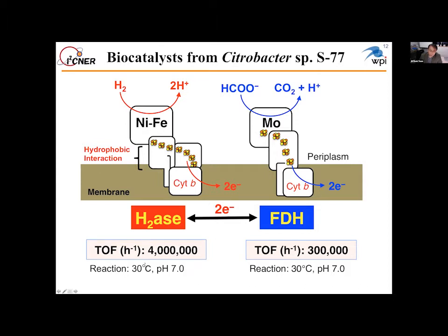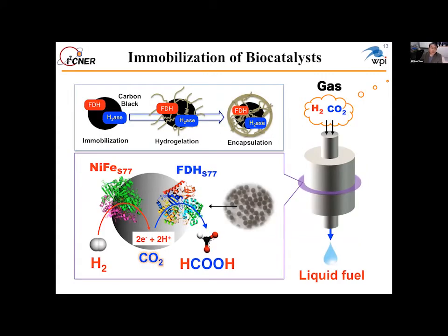Because as you see here, this enzyme is very active. Even in just 1 hour it's reactive, and it can last over a week, but even in 1 hour the activity is very high. Right? So if we can use this system, it's a very effective application. So now I combine these two enzymes on carbon and immobilize them, and we have the hydrogenase and capture this enzyme, particularly like this, and then use hydrogen and CO2, and it detected formate, made like this.